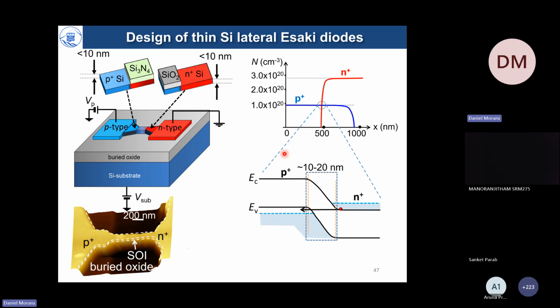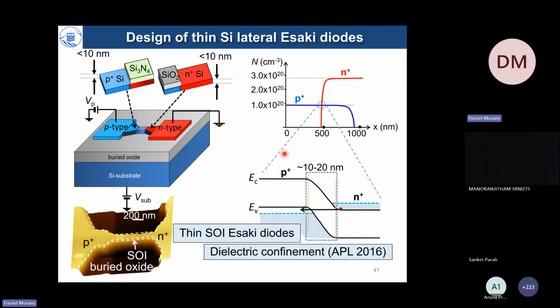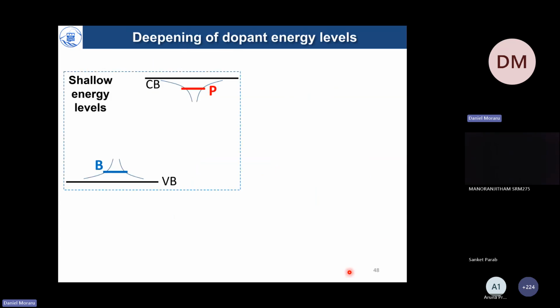With this said, we can now expect some effects due to thin SOI layers. Dielectric confinement will play a role, and I will explain a little about our Applied Physics Letters paper from 2016. At the same time, because we have many dopants in these depletion layers, clusters can be expected, and that was the core concept of this other APL paper.